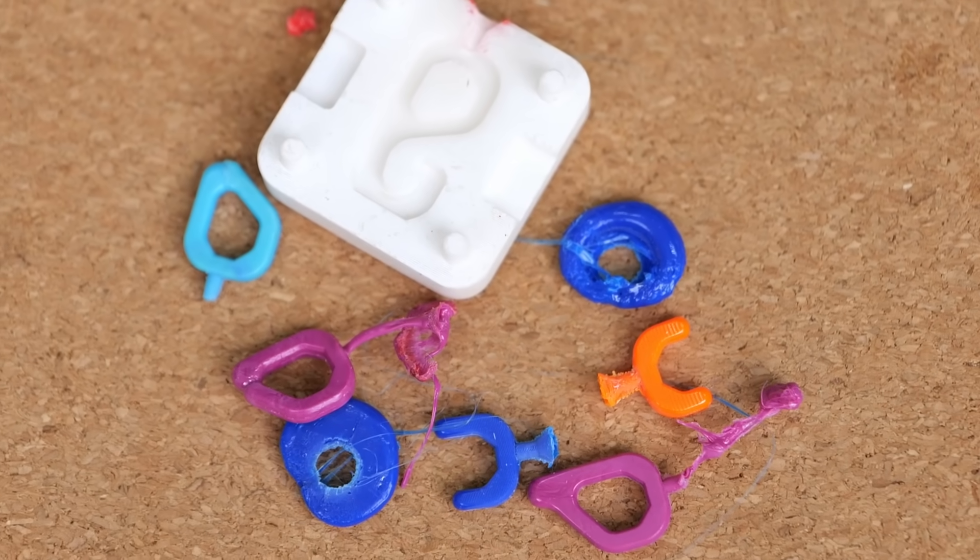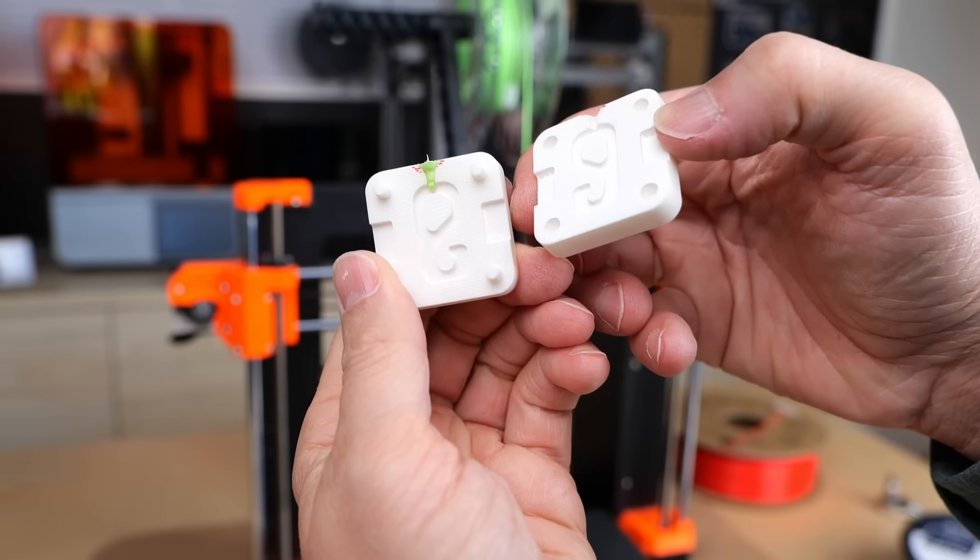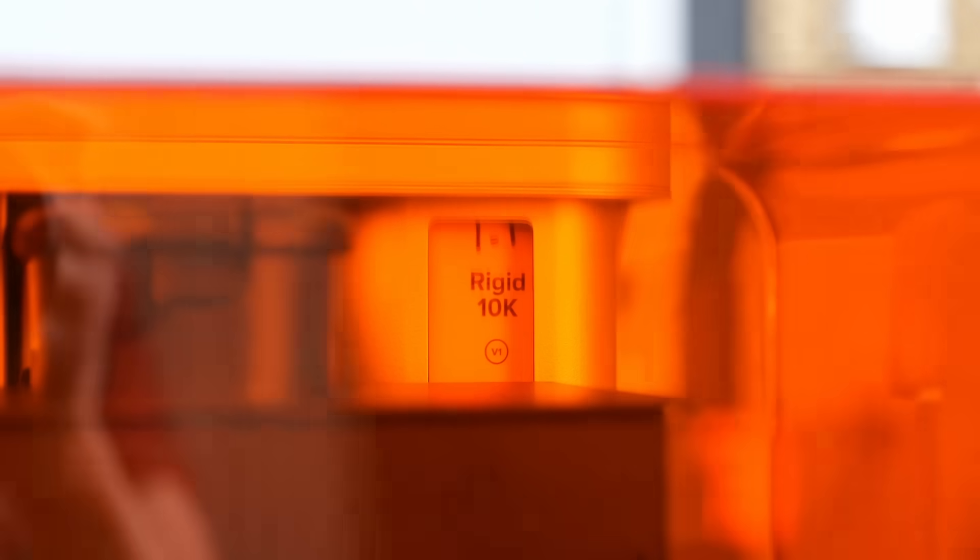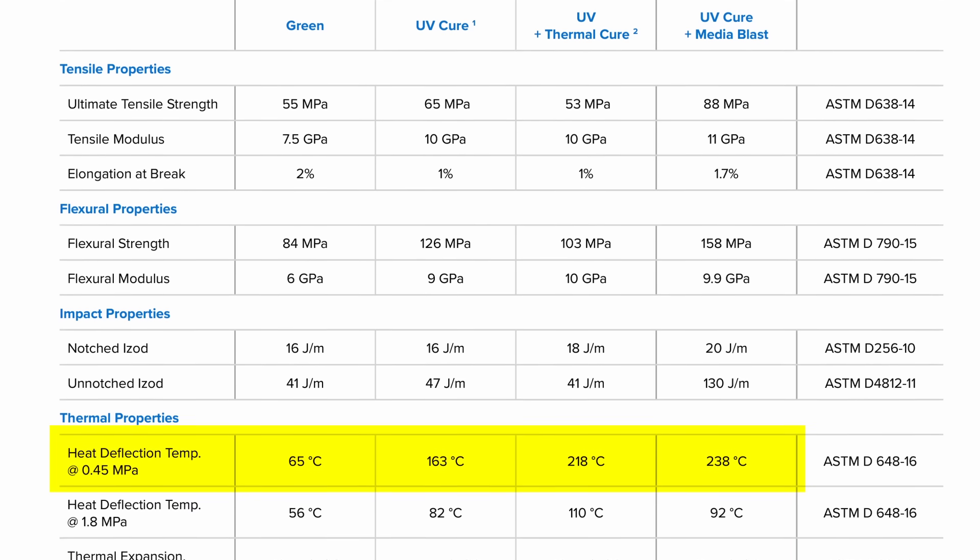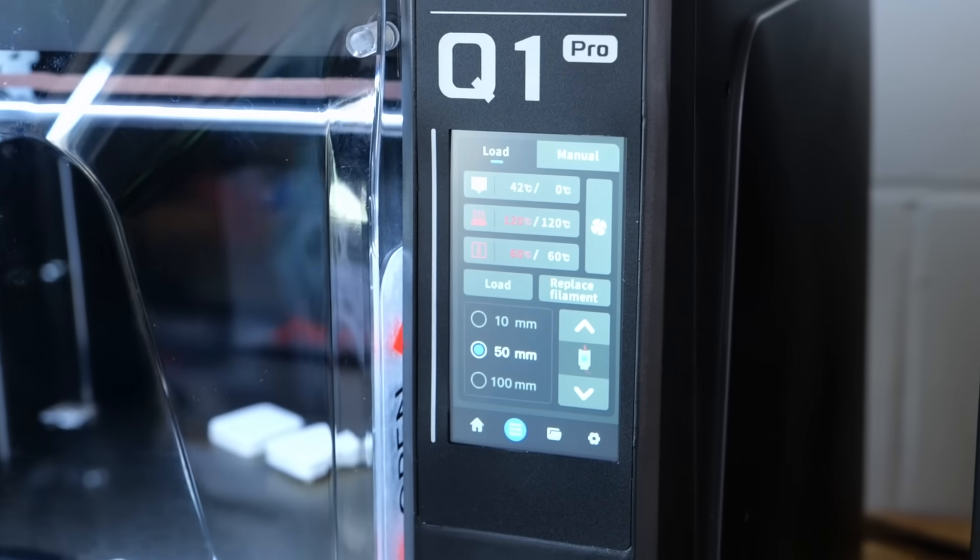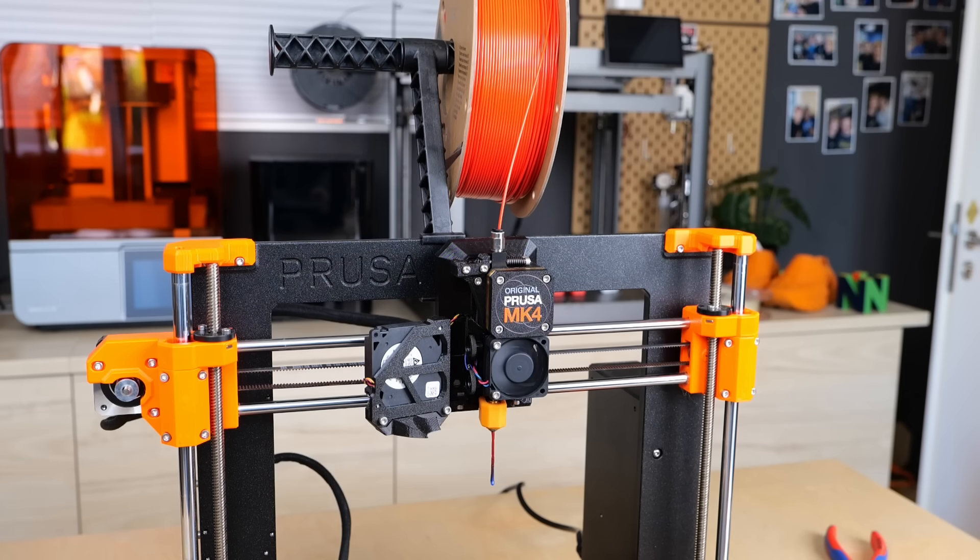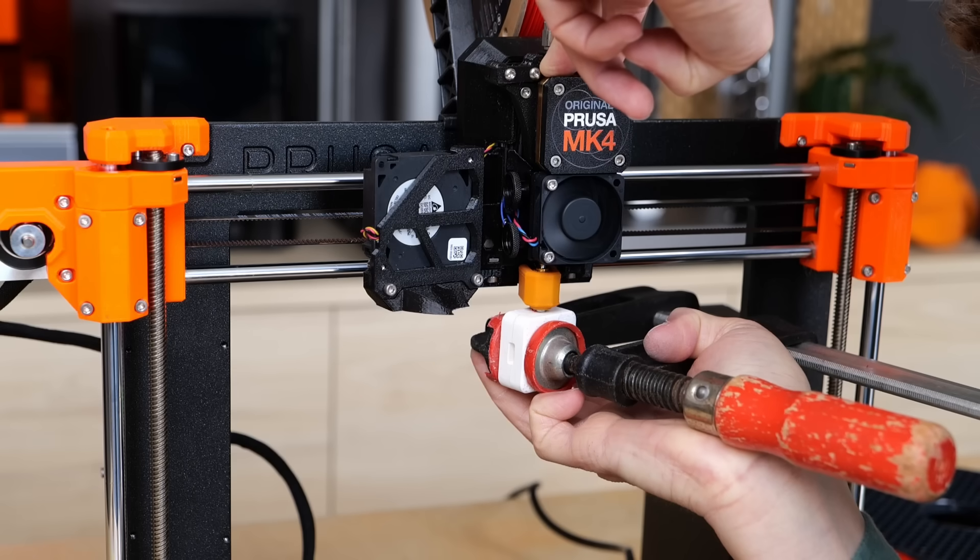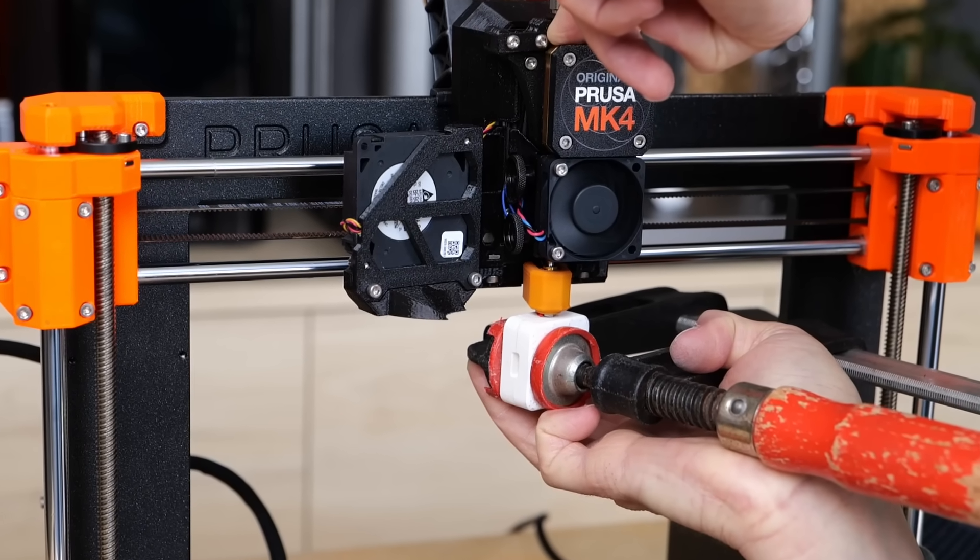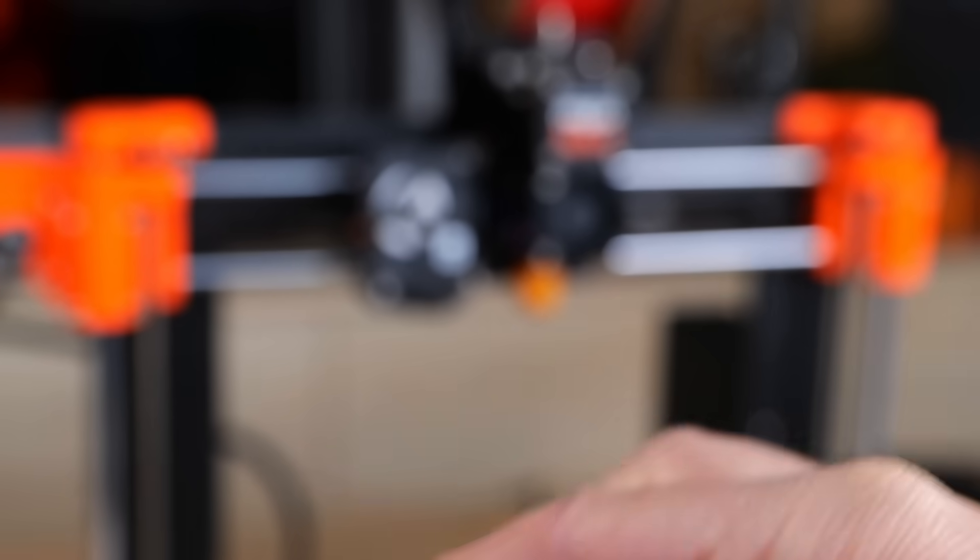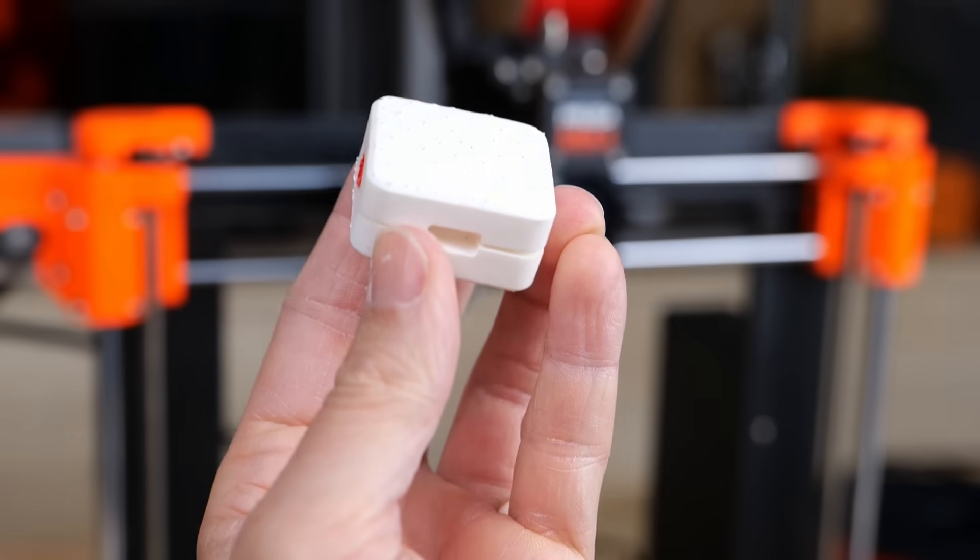So let's try to make this work. I think we have several issues that need to be tackled. First, the molten plastic cools down way too fast during the process and basically solidifies before it fills the complete mold. Formlabs Rigid 10K resin is totally fine even above 200 degrees Celsius. So I simply set my Qidi Q1 Pro to 120 degrees Celsius bed temperature and place the mold on the bed. While it was preheating I changed back to the high-flow PLA because it was the material I already had the best experience with. After around 30 minutes I took it out of the chamber, clamped it together and started pushing the plastic into the mold. This time it took a bit longer until the plastic seeped out of the sides, which was a good sign.